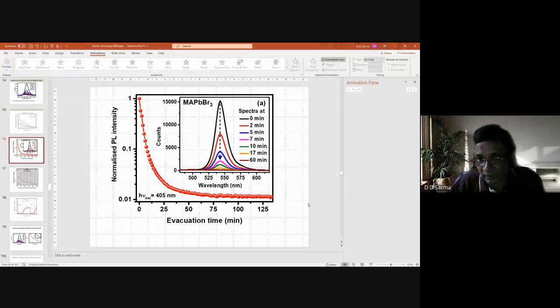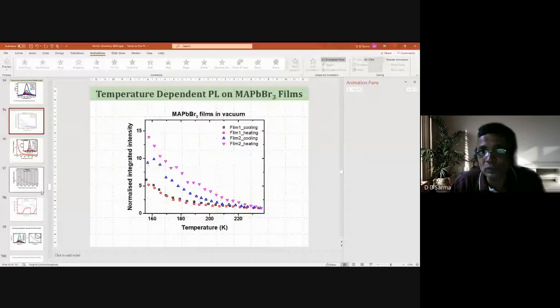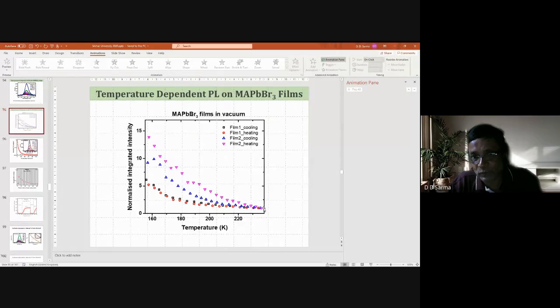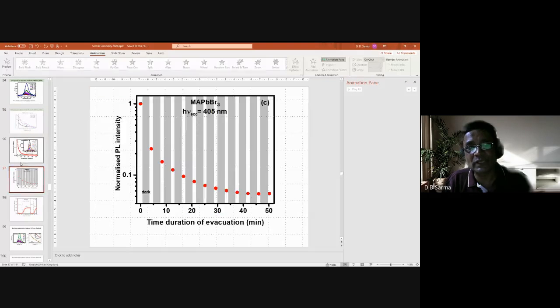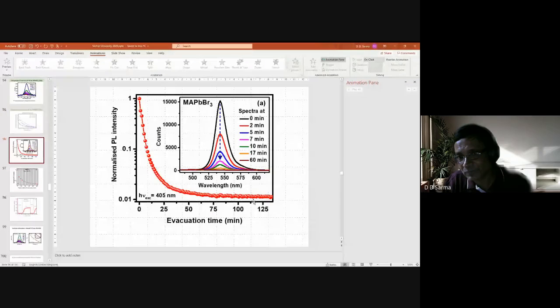One can say, okay, then come to this end where the photoluminescence intensity is not changing anymore and do the experiment there. But then you have such low intensity that your error bar becomes very, very huge, and you get very unreliable data. And here are actual attempts of ours before we realized. It's the same MAPbBr3. Different days we did the experiment, and this is the photoluminescence intensity as a function of temperature. You see that each of the runs looks different. If I fit it, I'll get different numbers for the excitonic binding energy. It is because we were doing the experiment at different points on this curve. You understand? So that's the reason.